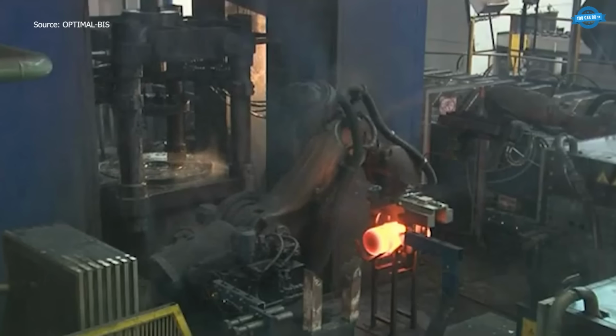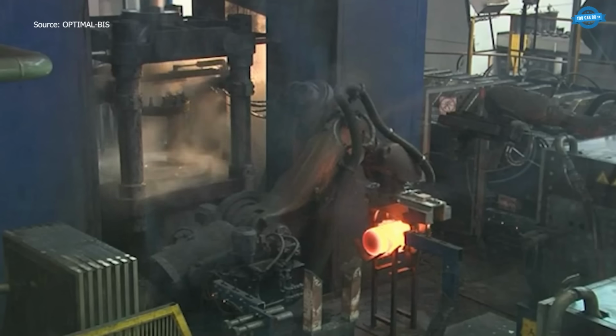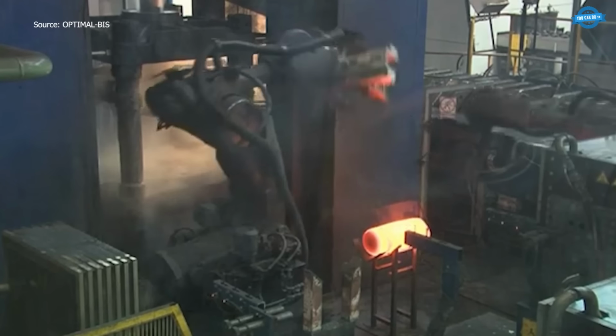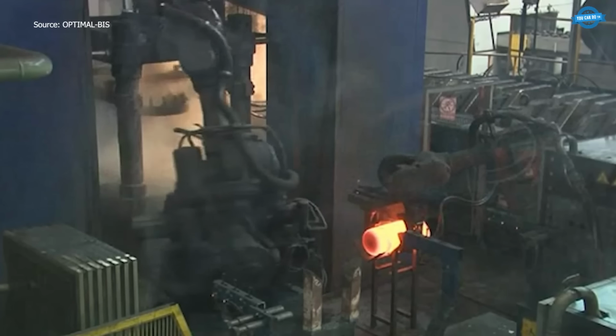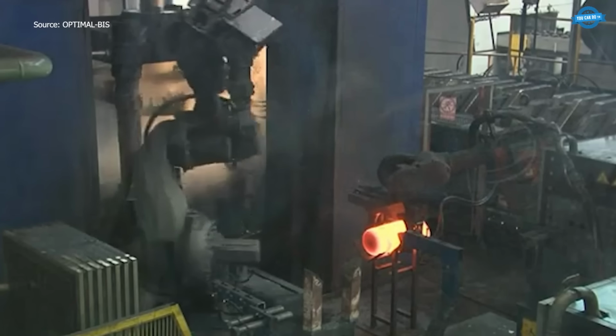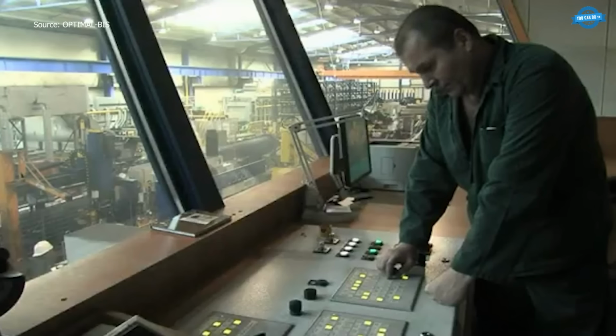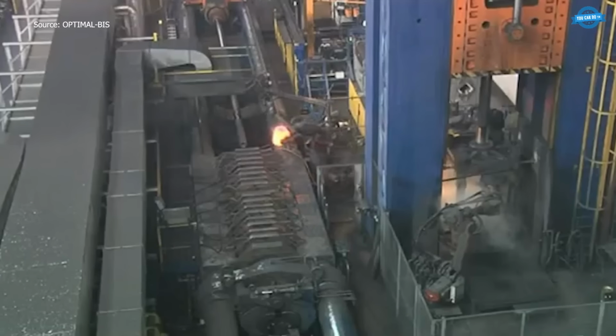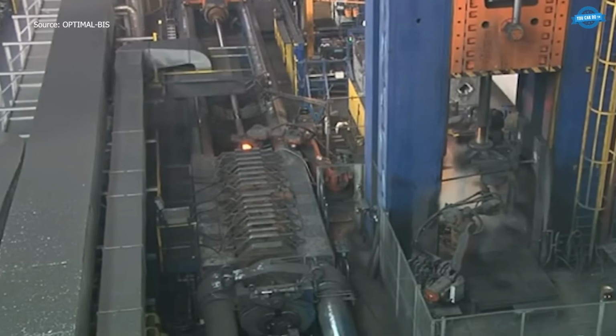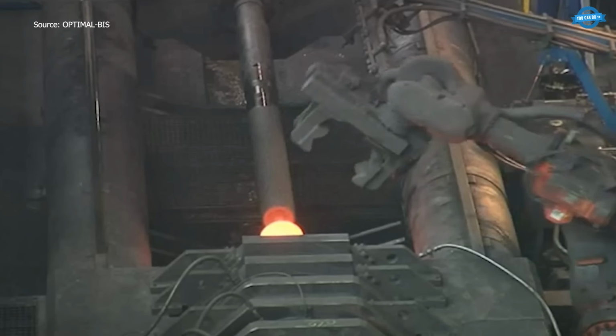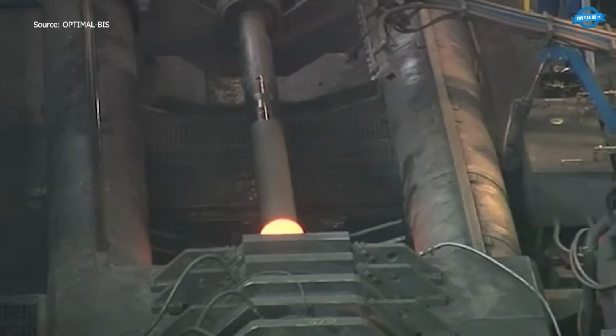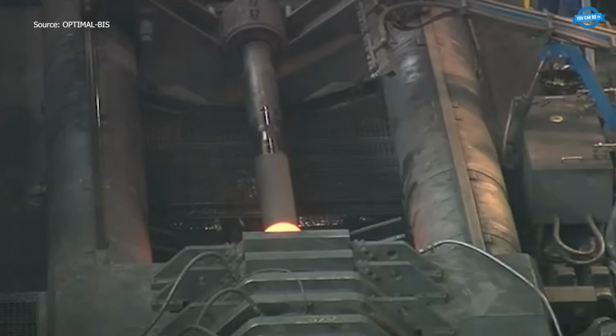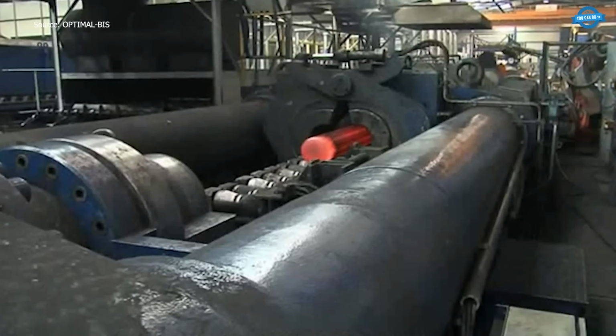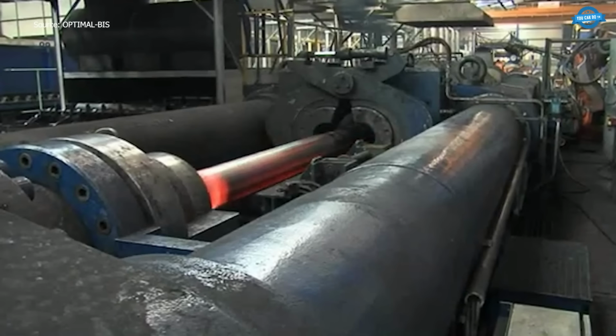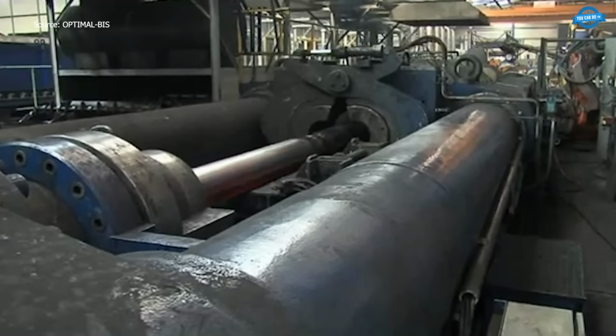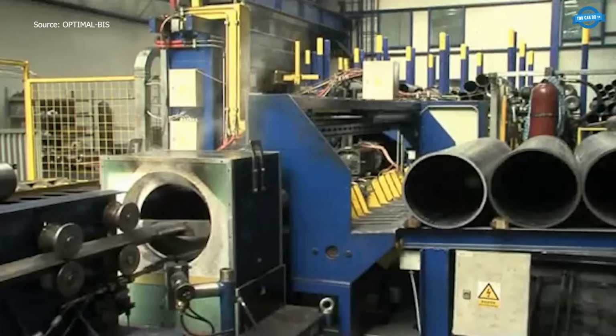Once the main body is formed, the cylinder's bottom and neck undergo refinement. Hot spinning ensures the neck and shoulder achieve structural integrity and airtightness. The hot spinning process creates a smooth transition between neck and body, reducing stress points. OPTIMAL-BIS calls this unique reverse extrusion technology, delivering seamless cylinders with consistent thickness, high pressure resistance, and reduced weight. Feels like you're seeing physics in action with every twist and pull.